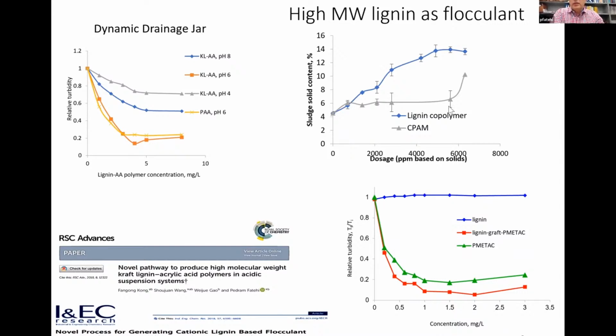When we use our material as a sludge dewatering chemical, we compared with CPAM. Why? Because CPAM is used commercially in pulp industry as a sludge dewatering material, and you can see that the sludge content, the solid content improved a lot. So we had a much better results using our own or in-house generated lignin polymer than commercially produced cationic polymer.